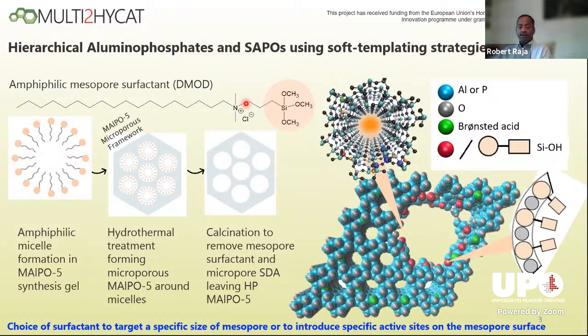So using this surfactant approach, having this silane head group gives us dual benefits and advantages. Apart from affording this secondary pore in the vicinity of this micropore, when you calcine the surfactant, you line these inner walls or cavities with these pendant silanol groups. Now, these silanol groups can impart some acidity, but also in terms of this project, they can serve as a functional handle for covalently anchoring organometallic and organocatalytic entities.